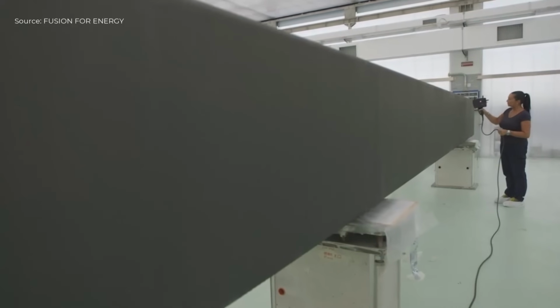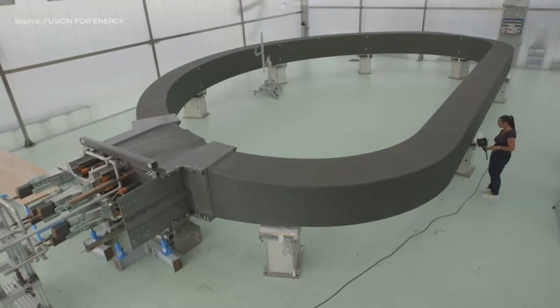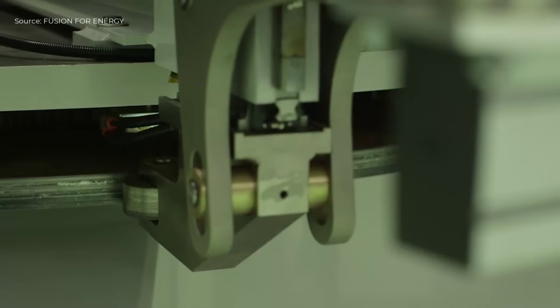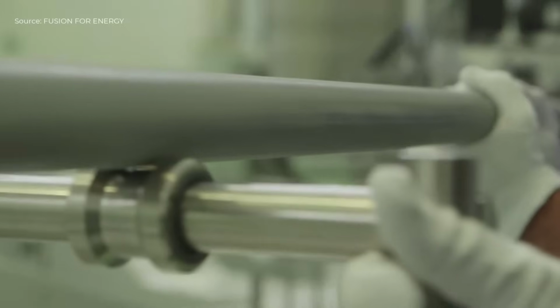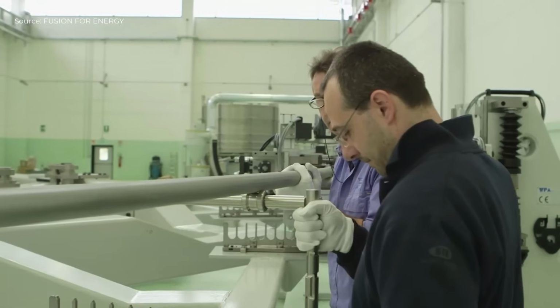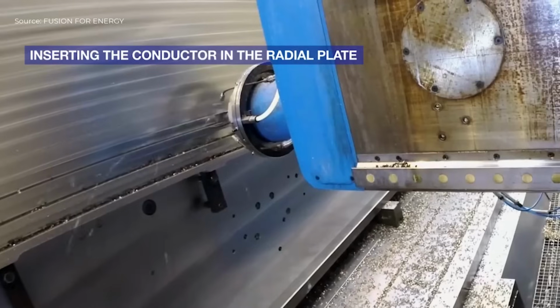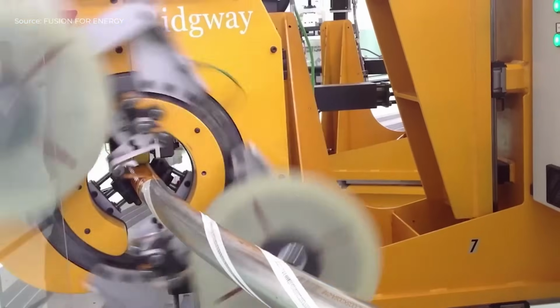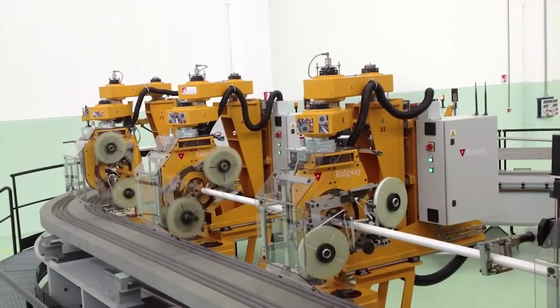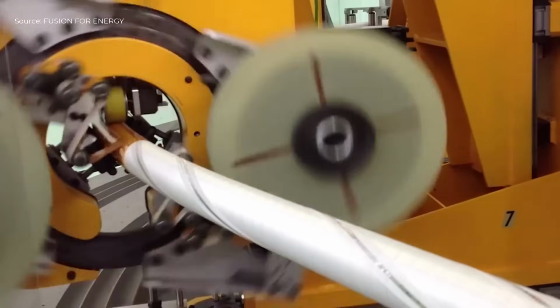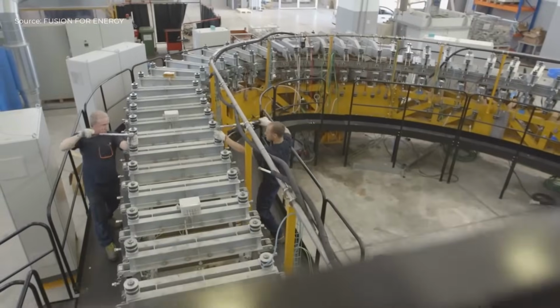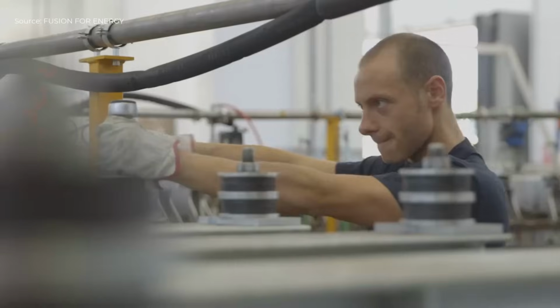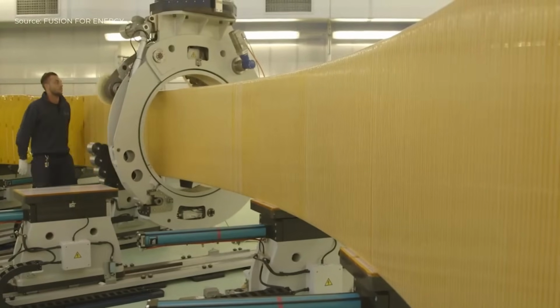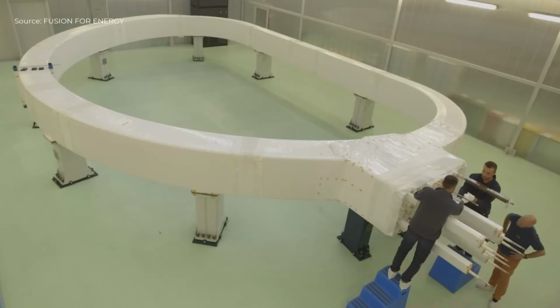The ITER toroidal field coil production begins by bending 750 meters of superconducting conductor into a double spiral to form a double pancake. After heat treatment at 650 degrees Celsius, the conductor is inserted into a grooved radial plate. It is then insulated with glass fiber and Kapton tape, locked with cover plates, and laser welded. 7 pancakes are joined, insulated, and vacuum impregnated with resin. After curing, dimensional checks and final assemblies are completed before transport and integration into the coil structure.